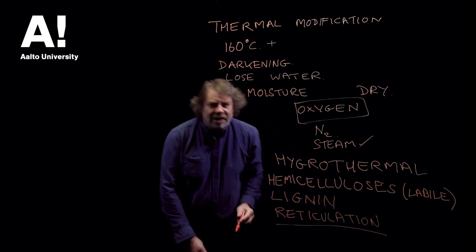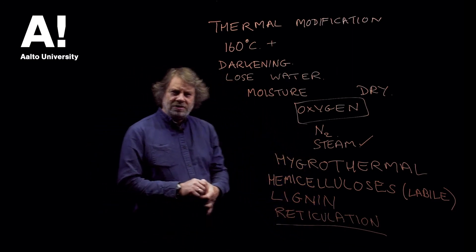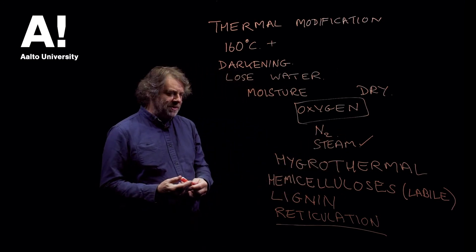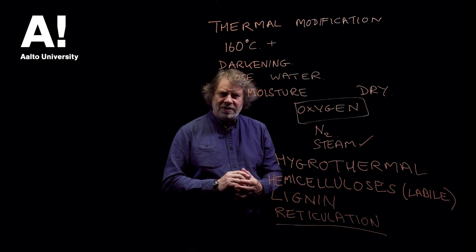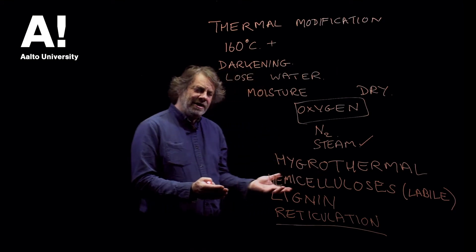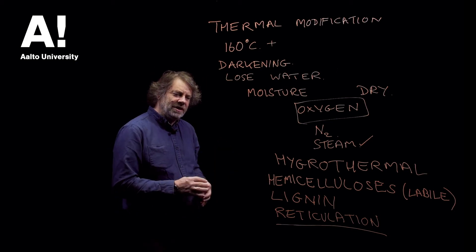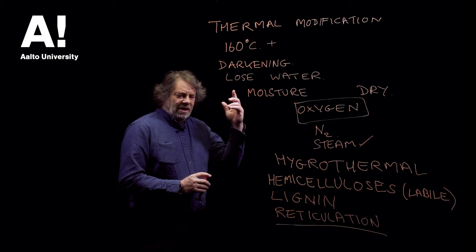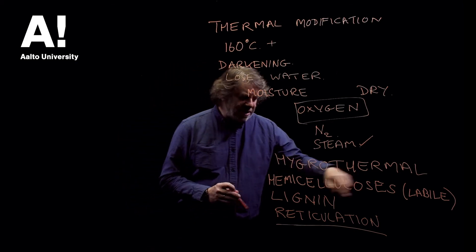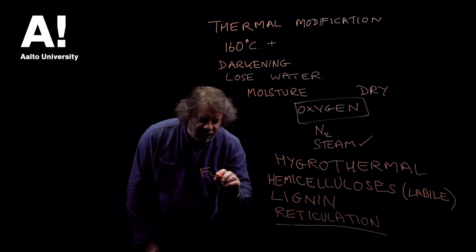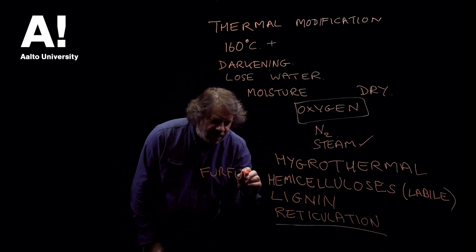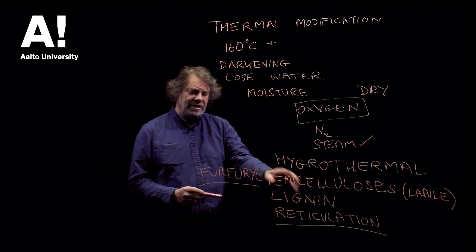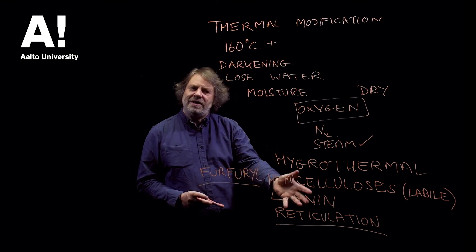Quite often when it comes to lignin you will see the term reticulation — I think it means cross-linking. I think you get extensive cross-linking with the lignin, but this is more a hypothesis than something that's been proved. We do get reactions of the hemicelluloses to form furfuryl compounds, and these can certainly be involved in cross-linking processes and will react with the lignin, so there's certainly something going on there.